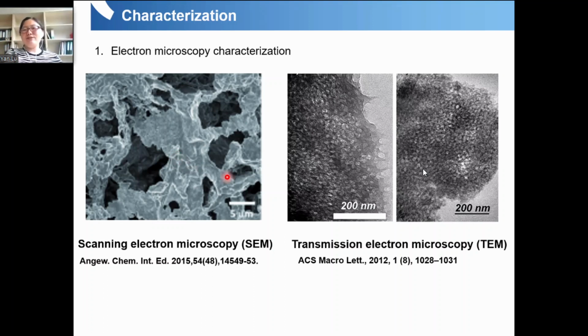But in some cases, you will have very defined mesopores around 2 to 10 nanometers. Then scanning electron microscopy is not useful in that case, because its resolution is normally quite low, and you need high resolution TEM. In this case, they have used high resolution TEM, so they can observe these well-defined small pores around 10 nanometers. However, if you have even smaller pore size, like 1 nanometer, these MOFs, then it's impossible to study them using electron microscopy, because the resolution is not good enough.